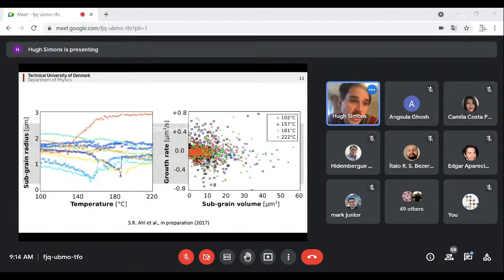And the beautiful thing is that by analyzing the intensities and the number of these subgrains in these images, we can use computer programs to make some statistics on them. Because we know that the volume of the grains is related to their brightness, you can estimate what their radius should be. So as the sample was heated, Sonia was able to make these statistics, tracking exactly what's happening to the individual subgrains.